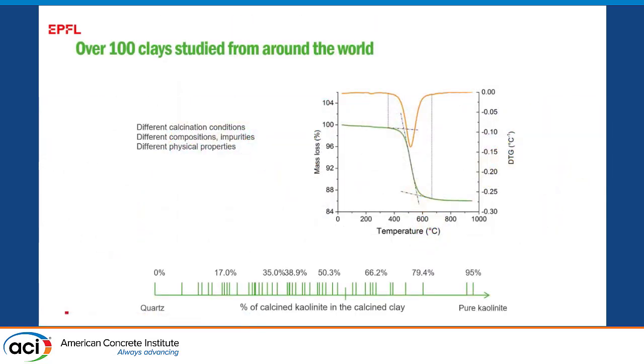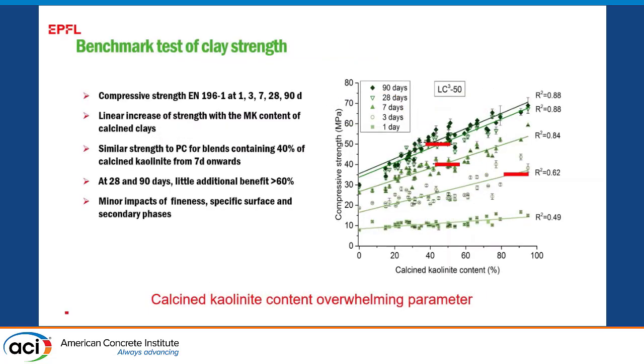And we can measure the kaolin very easily by looking at the weight loss between 400 and 800. We see it correlates really clearly with the strength development, and the red bars show the reference Portland cement. So at 7 and 28 days, we can get the same strength as the reference Portland cement with kaolinitic contents of around 30, 40, 50%, which are not used in other applications. People are often confusing the fact that we're talking about kaolinitic clays with metakaolin, which is a very expensive product and is used in many other applications.